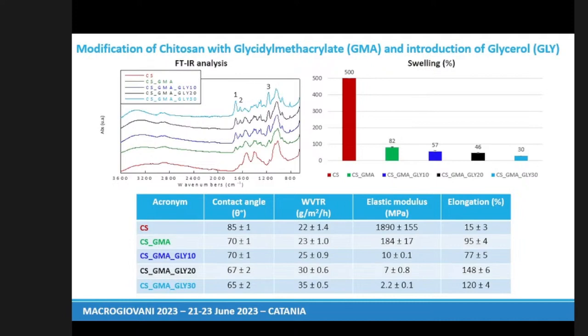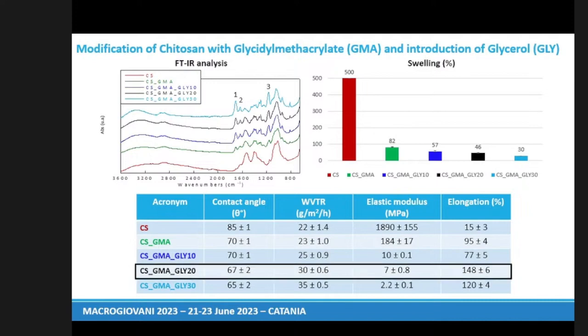Obviously, this functionalization modifies also the chemical-physical properties. In fact, we can see a decrease in the swelling capacity and in the contact angle associated with an increase in the water vapor transmission rate. Obviously, the introduction of glycerol caused a decrease in the elastic modulus, but only in the case of 20% of glycerol, we have the best elongation percentage. That is what we need for a good wound dressing.